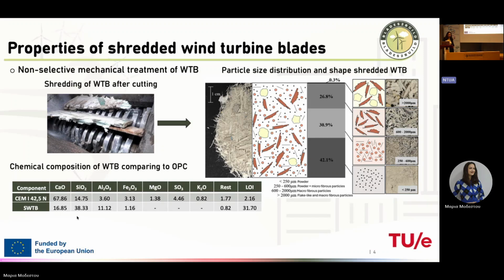So I suspect if we just used virgin glass fiber, we would have a significant effect. But since here we have, first of all, not a very high dosage of waste, and second, the glass fiber is mostly coated with polymer, it basically protects it from this reaction with the alkaline cement environment.